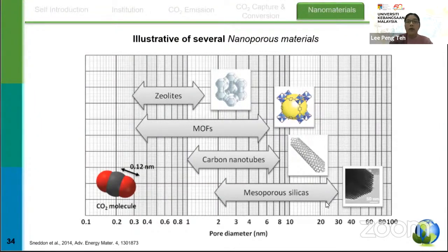Usually mesoporous silica, when we apply it in CO2 capture and conversion, we need to modify it. We can do surface modification, for example loading metal oxide, introducing amines, or grafting it with polymer. Why do we need to modify the mesoporous silica? This is because the surface of mesoporous silica consists of very mildly acidic silanol groups, SiOH. This is not really good for CO2 capture. CO2 itself is mildly acidic, so it will be attracted to an adsorbent that has basic properties. This is why we need to modify the mesoporous silica to enhance the basic property, as well as to enhance the CO2 adsorption performance.